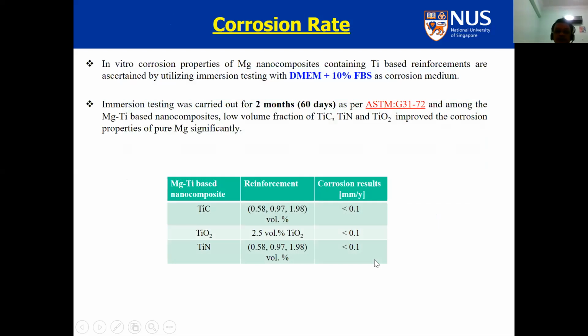Then we have to try these materials in a physiological medium, DMEM. It's a standard available medium in the market. You follow a certain ASTM standard, in this case G31-72, and you find the corrosion rate. The corrosion rate was 0.1 mm per year. So what does the surgeon want? What is this number actually? The surgeon wants about 0.2 mm per year and lower.